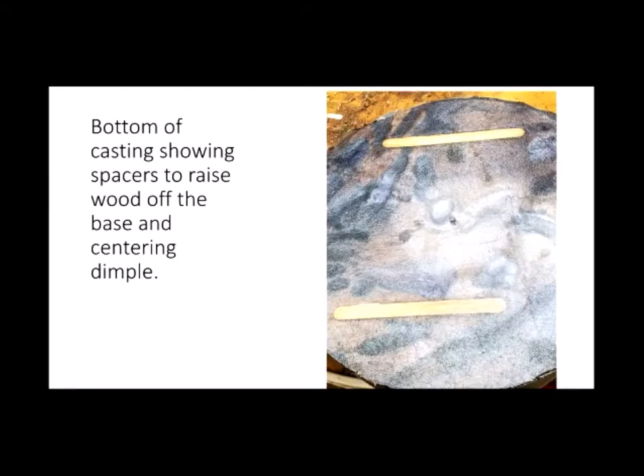This is the bottom. And a couple of things I would just want to point out here. When I do these big pours, I put a couple spacers underneath the block of wood, because a lot of times there's voids in the bottom as well. And if a piece is sitting down tight to the bottom, the resin often doesn't get in there. So you have to glue the spacers down to the HDPE base, and then glue the wood to the spacers, or else the wood will float up. But right in the middle of this, I don't know whether you can see my mouse, you can, that's that little nub that I was talking about,